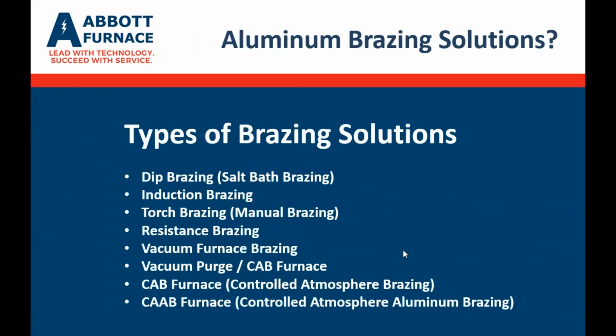There are a lot of different brazing solutions out there. Of course, we're going to focus on atmosphere furnace brazing, but some of the solutions are dip brazing or salt bath brazing. Induction is a process that joins multiple metals together using an electromagnetic field to heat the material without contact or a flame. Torch brazing uses a hot gas torch on or near a joint to melt the filler metal alloy to fill the gap. Another option is resistance brazing, joining two metals together by melting a low temperature alloy between them. And on the furnace side, there's vacuum furnace brazing, where the vacuum is pulled and the actual brazing is done in a vacuum chamber.